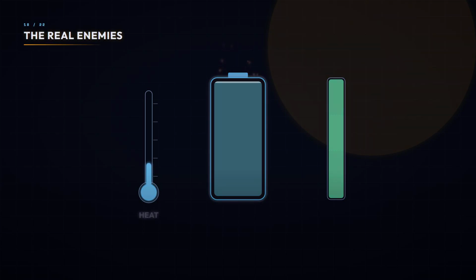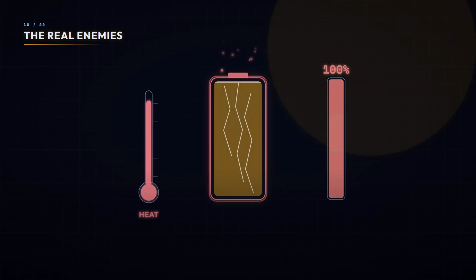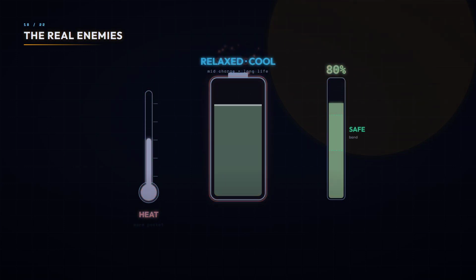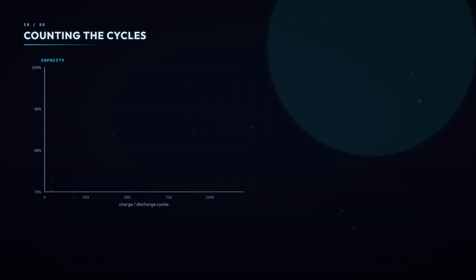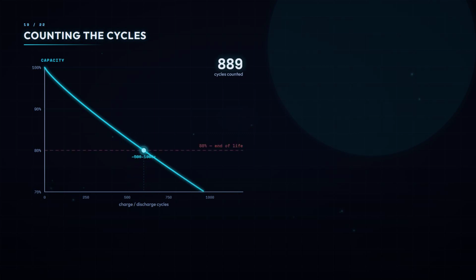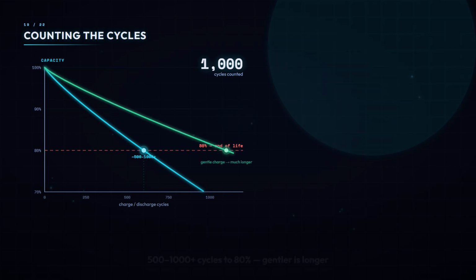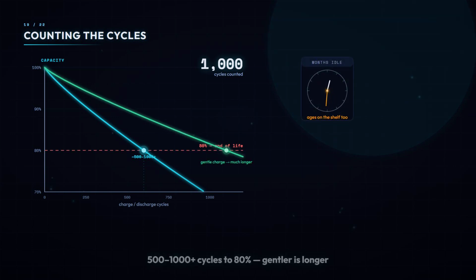2 things: heat and sitting at a full 100% charge. Dwelling fully charged in a warm pocket is more stressful to the cell than the act of cycling it. A cool middle charge is the secret to long life. Put numbers on it. A typical cell lasts roughly 500 to 1,000 plus cycles before fading to 80% capacity, and gentler charging stretches that far longer. It even ages just sitting in a drawer, so store it cool and around half full.